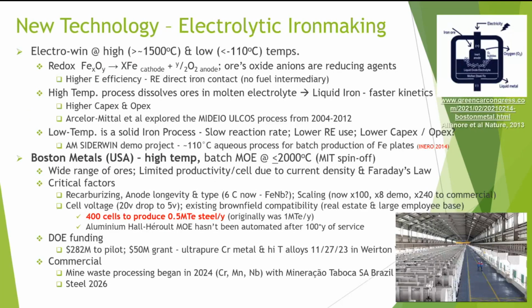Electrolytic iron making. Obviously, electrowinning can be either high temperature at 1500 degrees C or low temperature at about 110 or less. The redox reaction is iron at the cathode, oxygen at the anodes, and the actual oxide anions in the ore are the reducing agents. Higher efficiency because the renewable energy is direct contact. The high temperature process dissolves the ores in the molten electrolyte, giving liquid iron. Faster kinetics, but higher capex and opex. ArcelorMittal et al. explored this, MIDEIO, which came from the ULCOS work that was done. And they were looking at it between 2004 and 12, but I don't think it has moved forward.